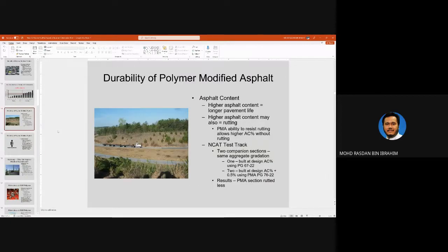So this is another test track conducted by NCAT, National Center for Asphalt Technology, for asphalt testing test track. So their research shows that higher asphalt content equals longer pavement life. Of course, because if you add more of the asphalt, the mix is going to be more flexible, more resilient, have higher resilience.